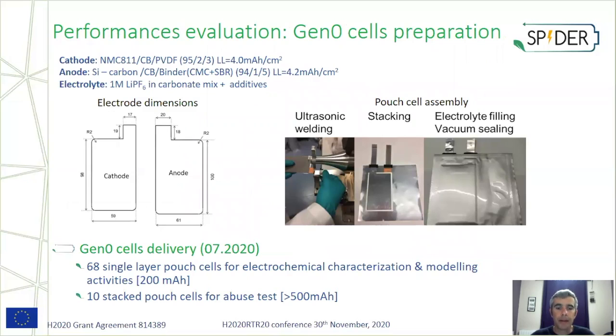We prepared the first cells generation composed of NMC 811, which is a nickel-rich commercial cathode, and silicon carbon composites for the anode. The electrolyte is a carbonate mixed with some specific additives developed during the first months of the project. You have the electrode dimensions. So we have pouch cells with electrode characteristics defined to fulfill the high energy density requirements. The pouch cell assembly process is shown here with ultrasonic welding, stacking, and the electrolyte filling before the final vacuum sealing.